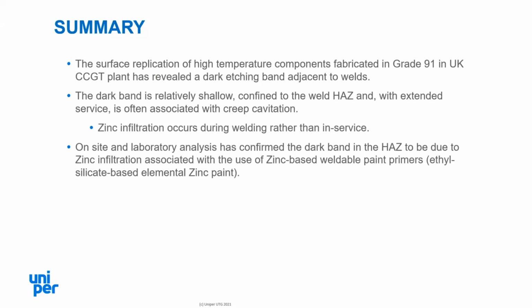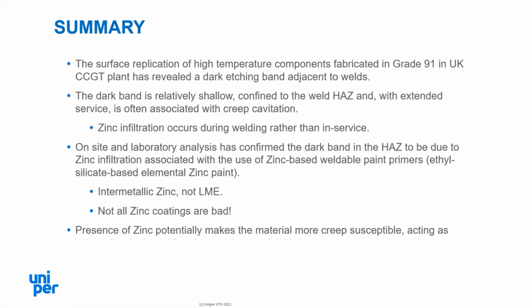On-site and laboratory analysis that we've undertaken at the Technology Centre has confirmed that this dark band in the heat-affected zone is due to zinc infiltration, not liquid metal embrittlement, and it's always associated with the use of a zinc-based weldable paint primer that contains elemental zinc. It's also worth noting at this point that not all zinc coatings are bad, but the assessment of the coating itself is prudent just to ensure that you've got a good zinc coating and not a bad zinc coating. And it's also found from our experience that the presence of zinc potentially makes the material, the grade 91 in this particular case, more susceptible to creep damage, almost seeming to act as a metallurgical notch within the component and prompting crack initiation.